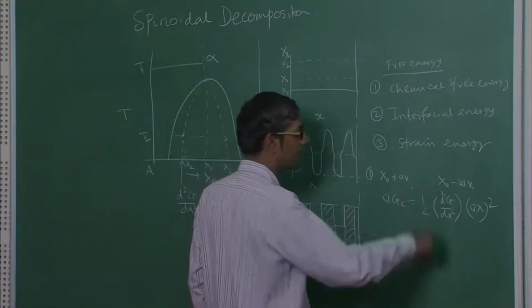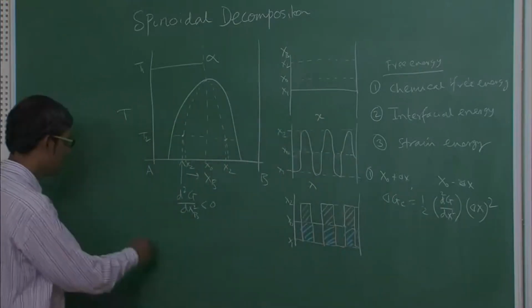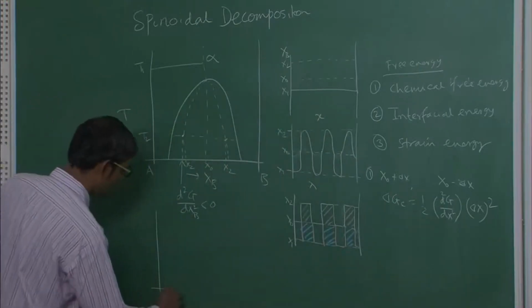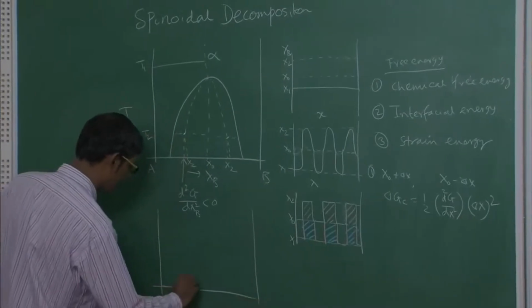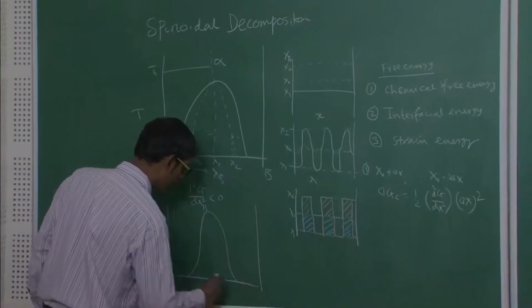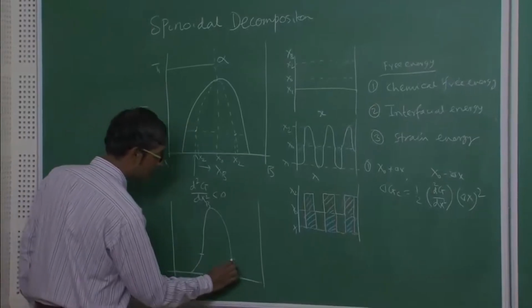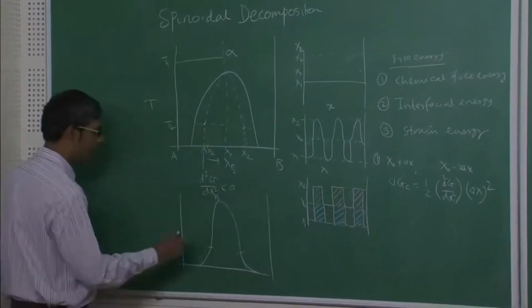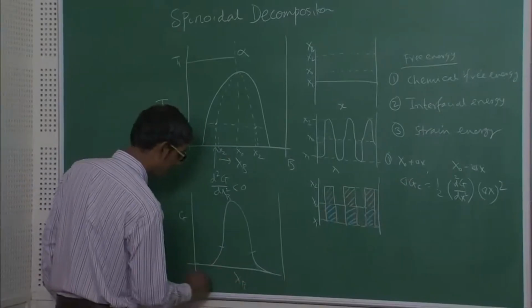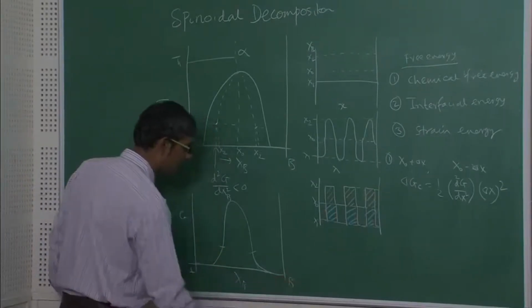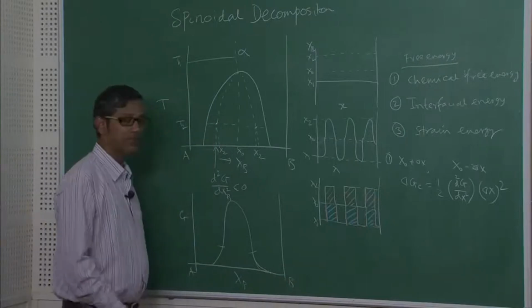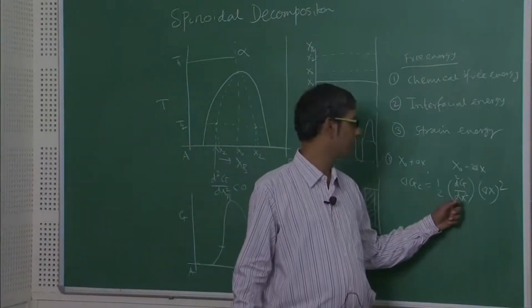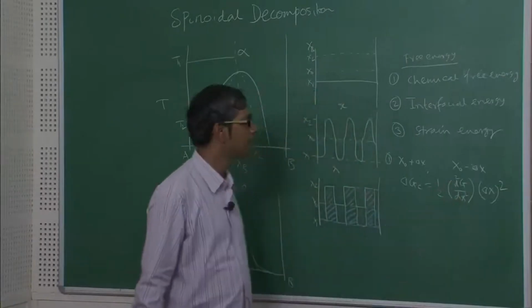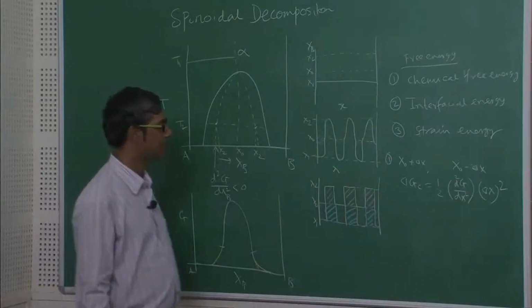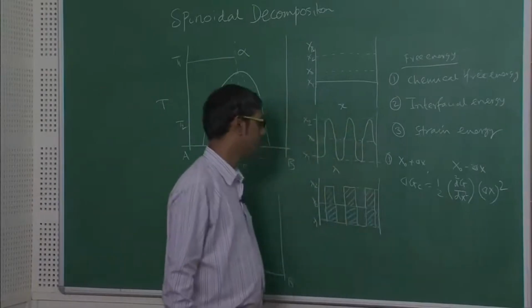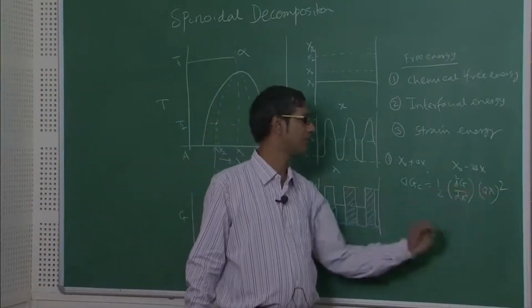Obviously, this depends on the curvature of the free energy curve. Why? Because the free energy curve, as you know, looks like this. Okay. So, there are two inflection points here where the curvature is 0. So, this is my G versus X curve. I have already discussed this in the first lecture. So, what you need to know is that the double derivative of G depends on X mostly. So, that we need to know, and then if we know the compositional fluctuation we can determine the chemical free energy part.